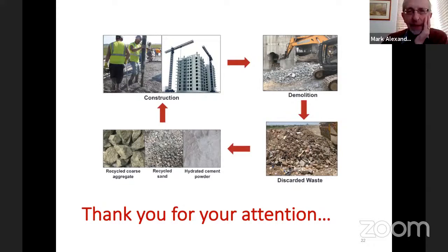Okay, but can you give us some idea? Is this heading in the right direction or not? What we have seen is that for 10 kgs of concrete feed, we need 2.5 kilowatts of electrical energy. But we have still not worked out the full picture, so I cannot answer all the questions. But I think there are some methods of solar heating where we can directly heat this mass, and we will be able to do the same process with that.